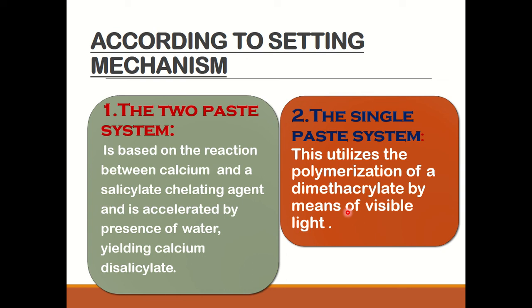The single paste system has certain advantages over the two paste system. They set on command — unless the light is applied, they are not going to set. They also have improved strength, no solubility in acid, and minimal solubility in water compared to the two paste system. However, as per various in vitro studies, the antibacterial and bioinductive properties of this light-cured, silica-based calcium hydroxide system are less than those of the chemical-cure calcium hydroxide paste.